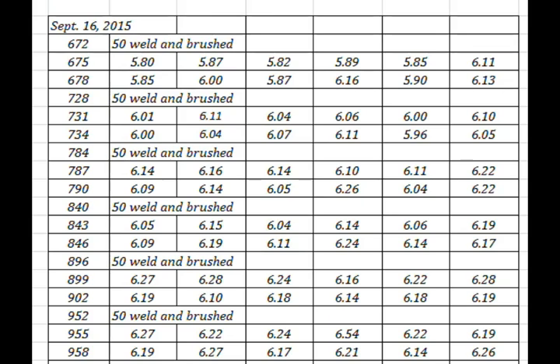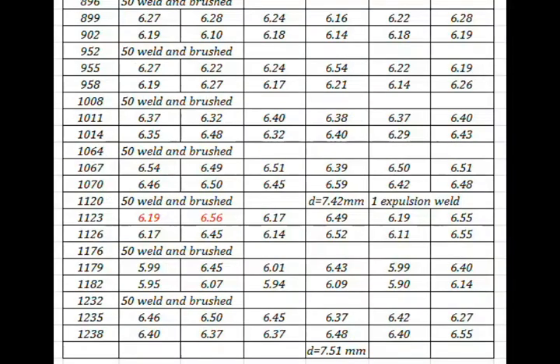The second day I welded another 566 welds. At weld 1120 the cap diameter was 7.42 mm, and at the end of 1240 welds the cap diameter was 7.51 mm. The starting current was 10.0 kiloamperes, and after 1240 welds the current increased to 13.2 kiloamperes. The increase of current is used to compensate the increase of cap diameter. This way the temperature will be kept constant.